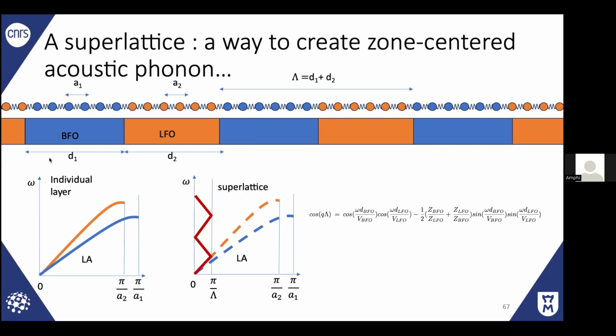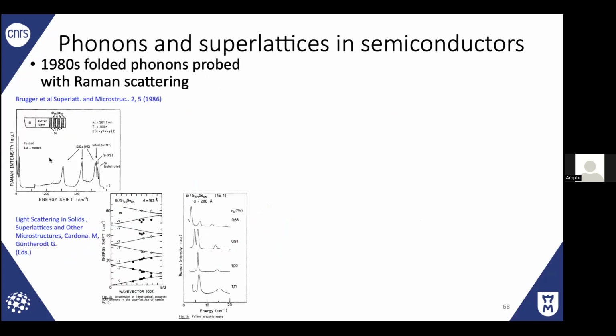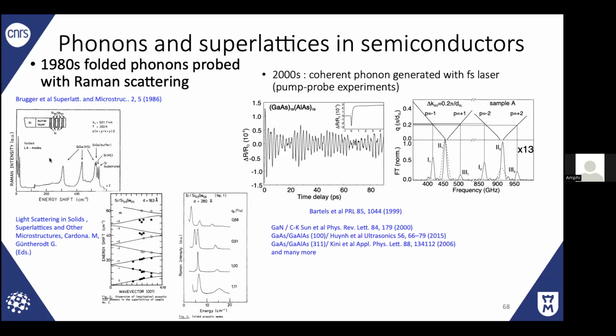This is a bit complicated. This is the dispersion relation. Of course, superlattices have been known since the 80s. People have built lots of different superlattices for electronics; for example, quantum cascade lasers are superlattices. And for phonon heat transport as well. And a bit more than 20 years ago, people also did it with pump-probe experiments, and they perfectly showed that it is possible to generate nearly THz frequencies thanks to the mode folding.